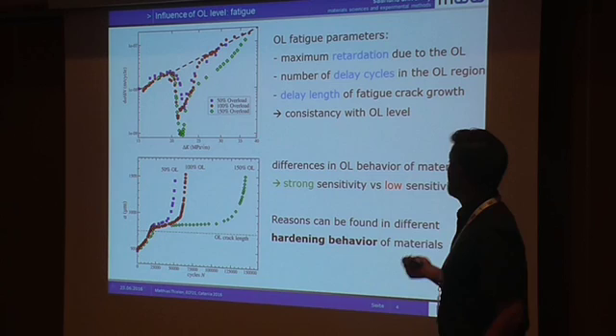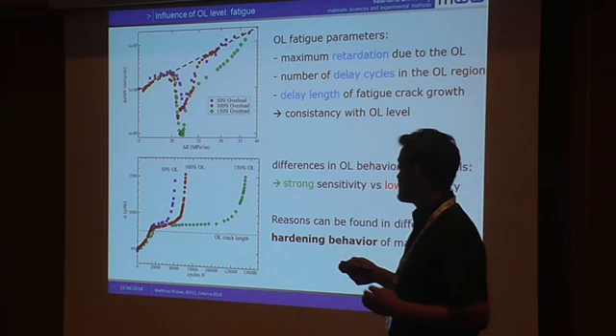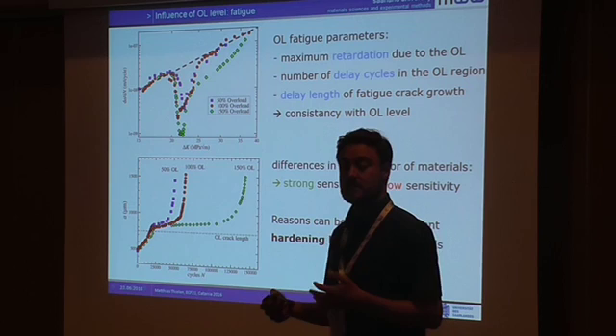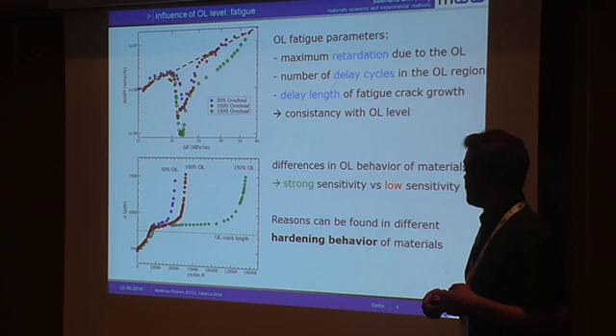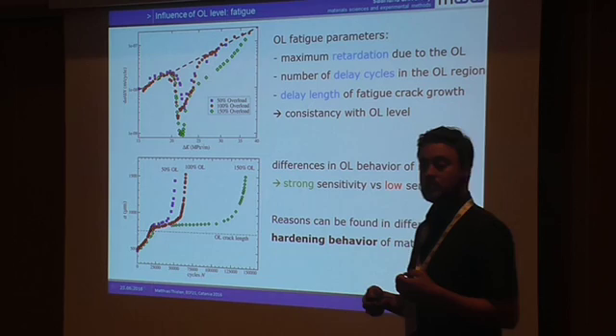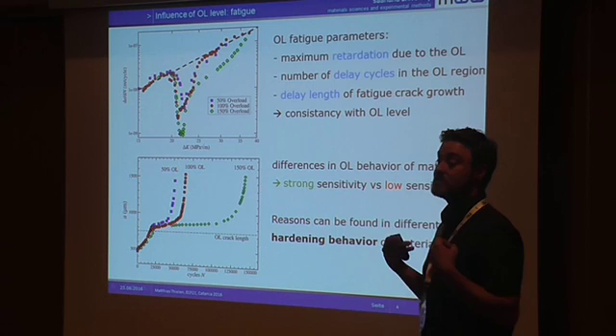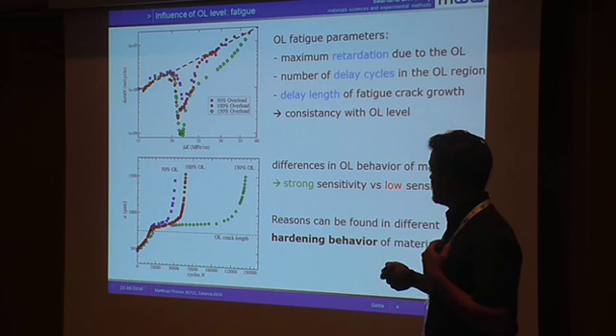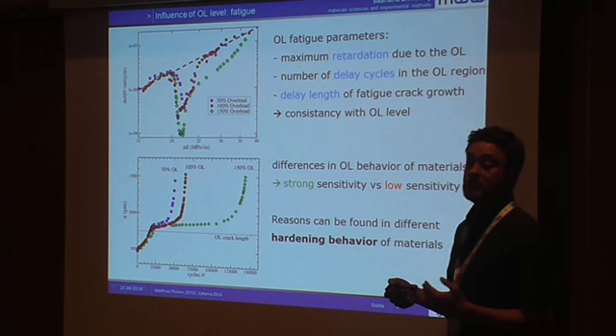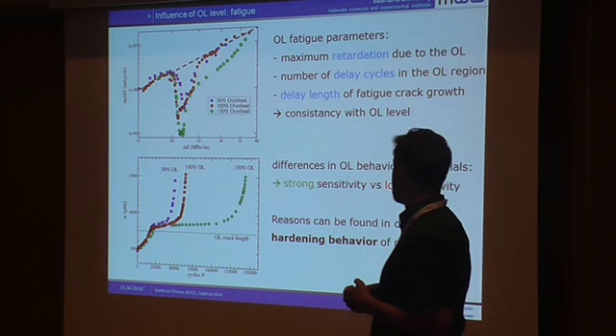As a material scientist, I was asking myself which role the material plays in all of this. Comparing this curve with results shown by Professor McGill this morning, the qualitative behavior is the same, but with a different material there were not as many delay cycles. If you look at the literature, there are materials with a strong sensitivity to the overload effect and materials with weaker sensitivity, and the reason for this can be found in the hardening behavior of the material.